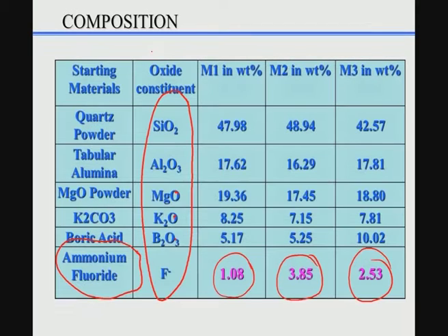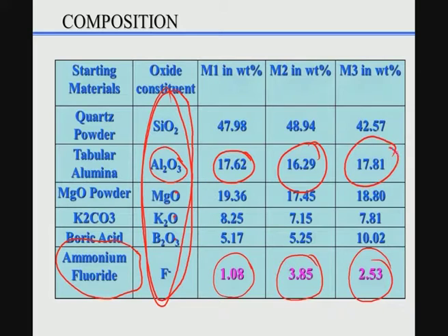In other words, if you use alumina crucibles to melt this particular glass composition, what will happen? You have alumina in the base glass, right. Now, if this composition is melted in an alumina crucible, there will be additional alumina pickup from the crucible. So this targeted composition or initial composition will not be the same as the way you are showing in the table. It will be disturbed.